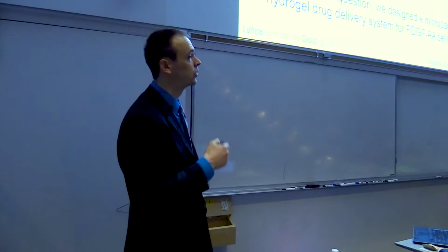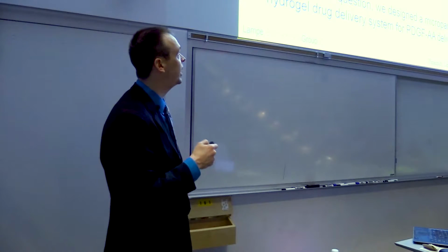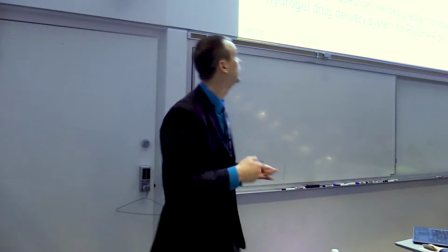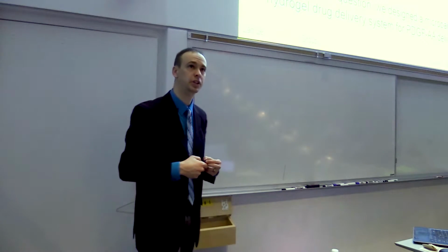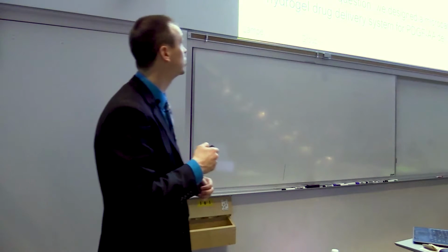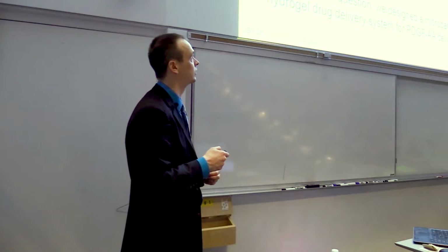So in this case, we can add this PDGF-AA. So this is a soluble growth factor. The GF stands for growth factor, right? And we can add that in, but we control the rate and dose of that molecule by making these PLGA microparticles. This is a pretty common material; PLGA is used for degradable sutures, for instance. But we can turn it into microparticles and encapsulate this molecule inside of those and change the polymer to change the rate of release. So we have a slow release and a fast release, right?